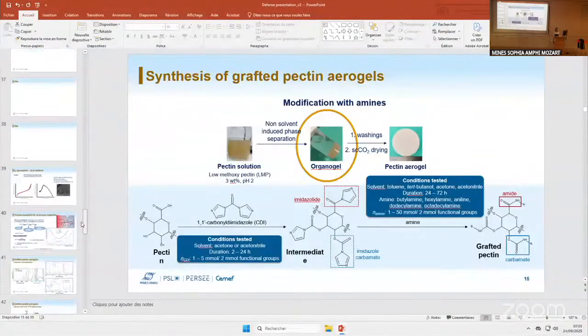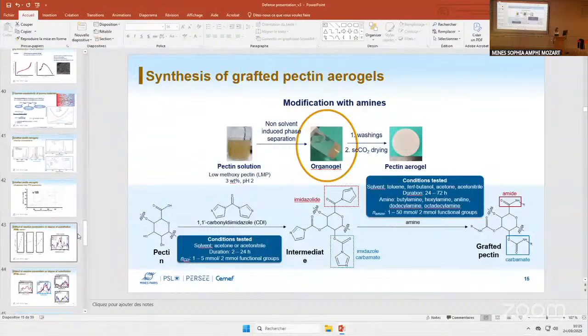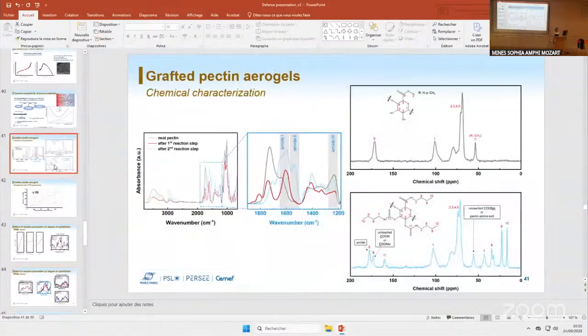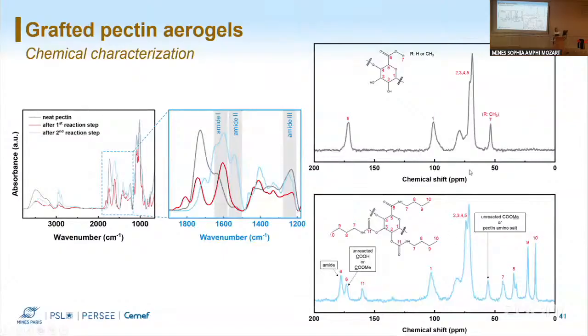I have slides, but I didn't find this data. Maybe it is given. So these are the NMR spectra. We used carbon NMR. We know that it is not exactly quantitative. Yes, it is semi-quantitative. For this reason, we are always very careful to estimate the DS and not calculate it. And we want to continue with elemental analysis, to really see what the degree of substitution is, because pectin is not